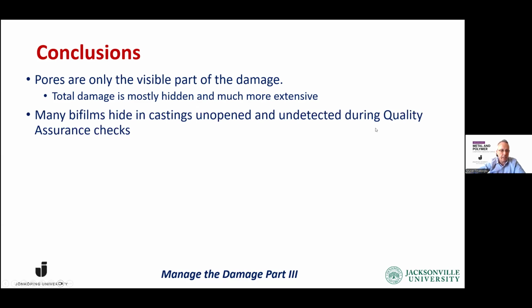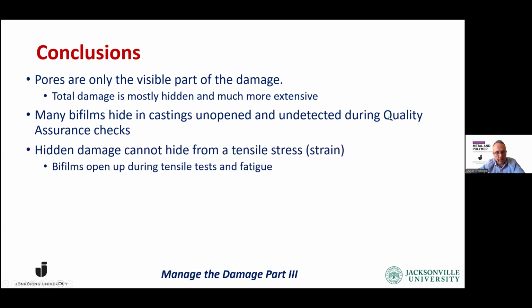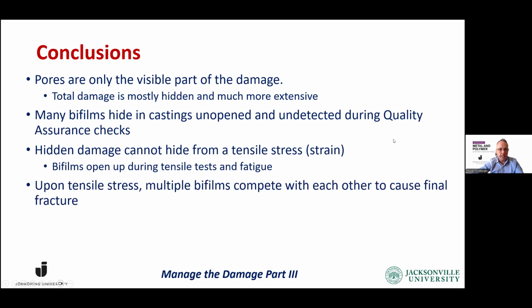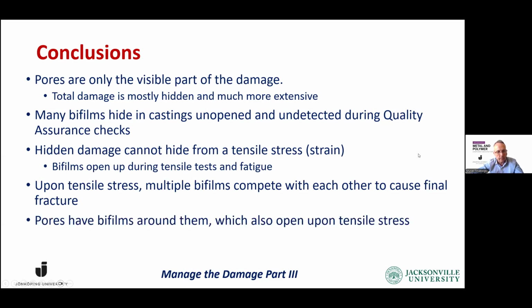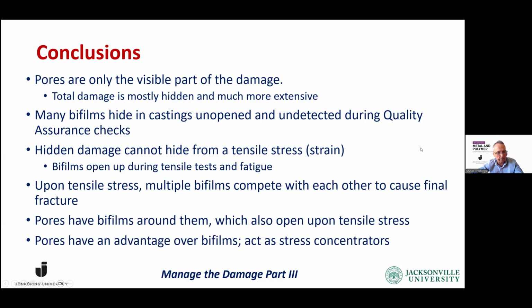Many bifilms hide in castings. They remain unopened and undetected during quality assurance checks, especially if you rely on X-rays or CT scans. You cannot see them. One thing they cannot hide from is a tensile stress. They open up during tensile tests and fatigue testing. Upon tensile stress, there is a competition between multiple bifilms to cause the final fracture. All pores have bifilms around them, which also open up under tensile stress. What pores do is act as stress concentrators, so the bifilms next to them have a larger chance of winning the competition to the final fracture.